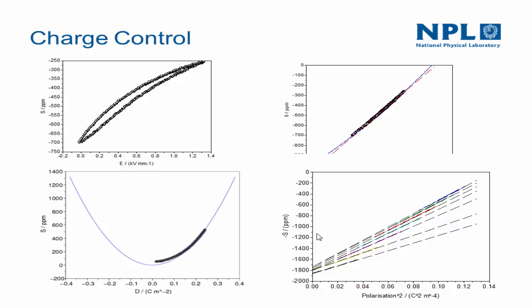It also tells us something about charge control. Charge control is a method often used for linearizing and removing the hysteresis in a control system using a piezoelectric device. And you can see that, I'm sorry, but the axis has disappeared, but this is charge along the x-axis, that's strain, and you can see that as we go up and down the loop, there is no hysteresis and it's very linear. It's actually not quite linear. It again follows this electrostrictive parabola.